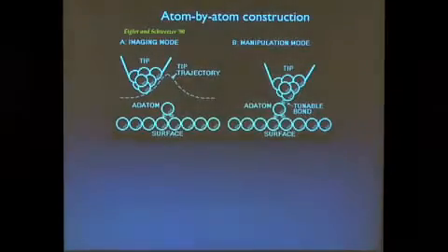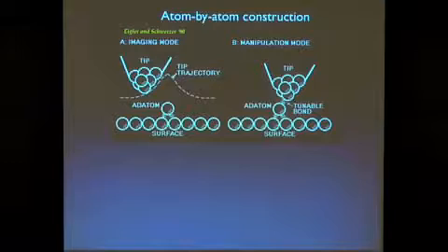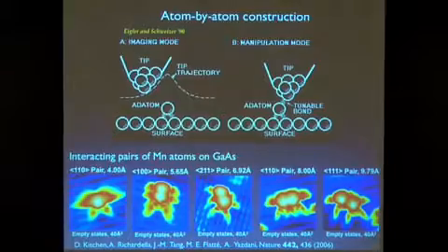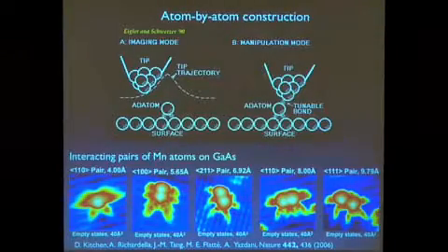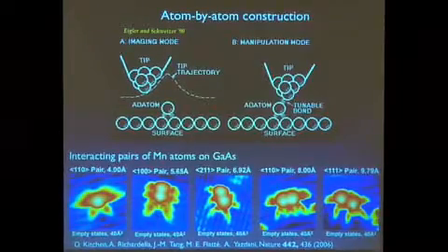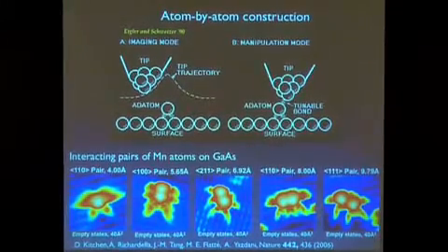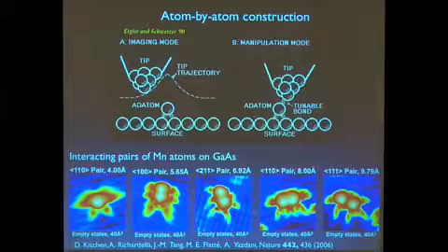OK. So how do we do this? Well, that's one of the powers of the STM. You can actually fabricate structures using the STM. We have done this, for example, with other kinds of spins, like spins in semiconductors. These are experiments done a few years ago in which we actually put spins in gallium arsenide and watched them interact with one another, just spins at different distances relative to one another.